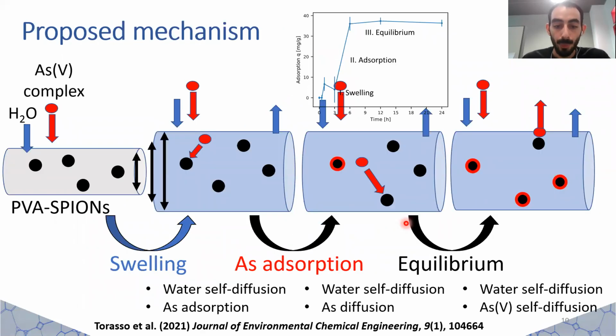Here, we show a schematic representation of the adsorption mechanism proposed by us. Red and blue dots represent arsenic and water. During the first hour, the nanofibers increase their diameter and solution flows inward, not altering the solution arsenic concentration. Once the fibers are wet, diffusion of arsenic begins inside the nanofibers, and it can be adsorbed by the nano-magnetite within. These results were published last year in the Journal of Environmental Chemical Engineering.